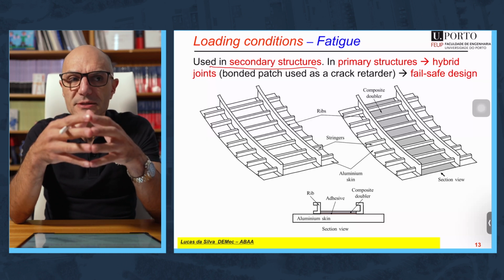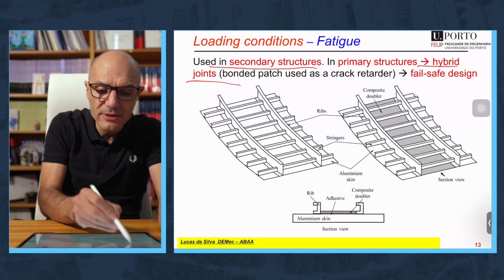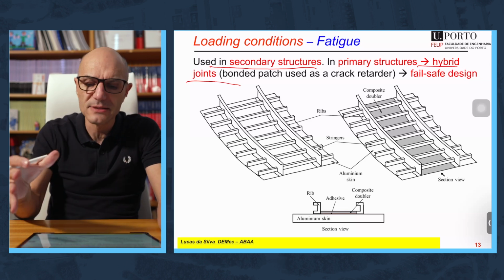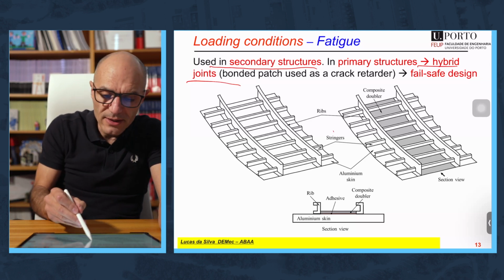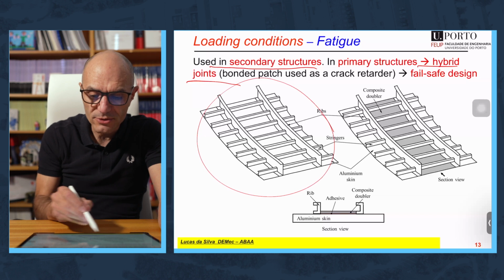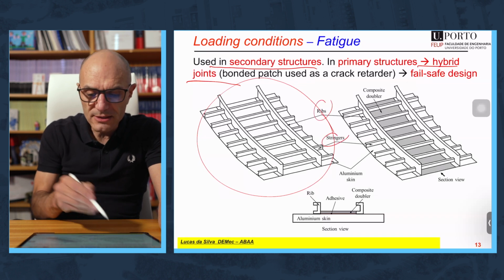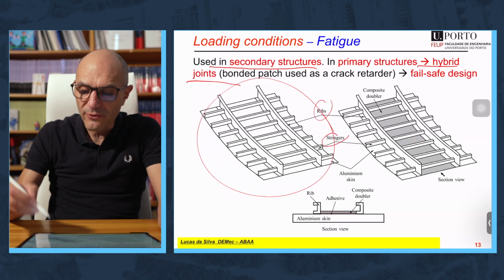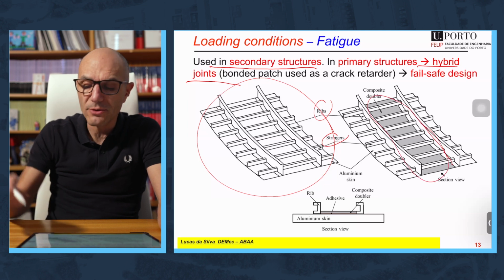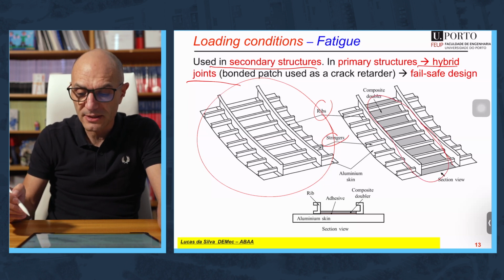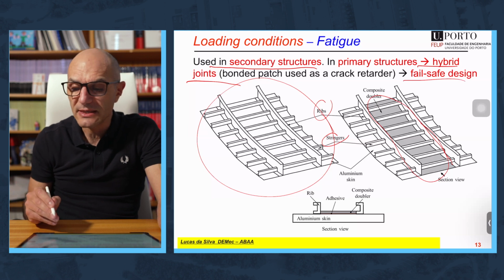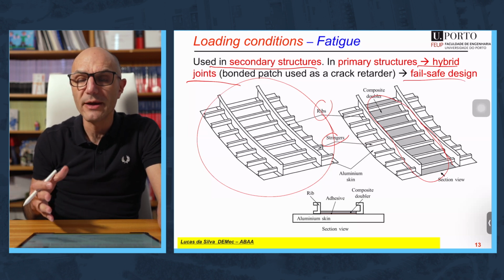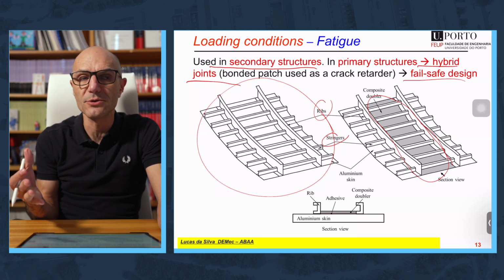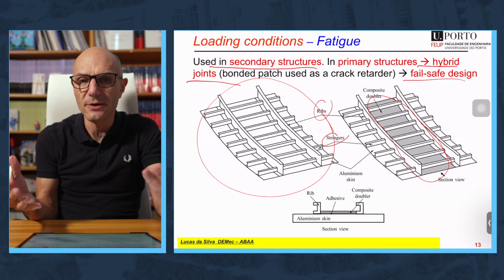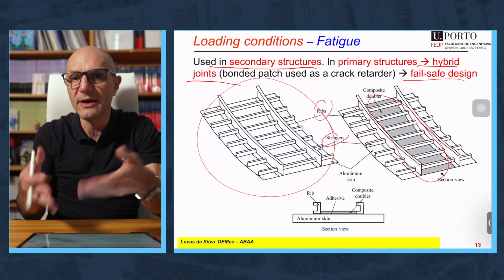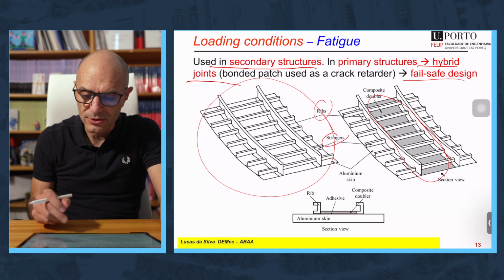If they are used in primary structures, then they are used with hybrid joints. That means you put the adhesive plus something else. Imagine the fuselage, you have the stringers, you have the ribs. This in general is reinforced with a patch adhesively bonded. Then you have a hybrid joint, you have the rivets plus the adhesive. And this is in line with the fail-safe design approach that is used in aircraft, where in case one fails, you still have the other one. It's much safer, and this, in fact, is used in primary structures.